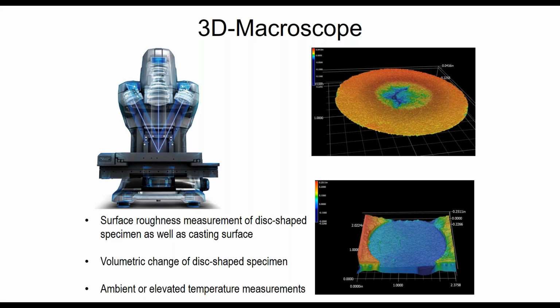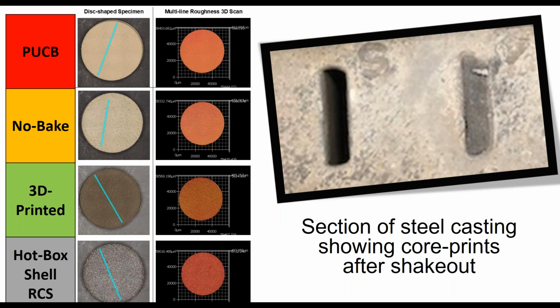We can get surface roughness, volumetric change, ambient temperature differentials. We can have that data. So any shift between the molding room to the finishing room, we know that digital data, that digital shift, we could be responsive to and give information back to the foundry in near real time. So regardless of the process, we need to qualify the sand binder systems for the head pressure, temperatures, and chemistry.